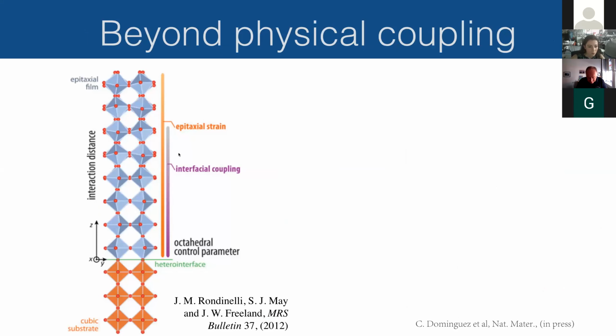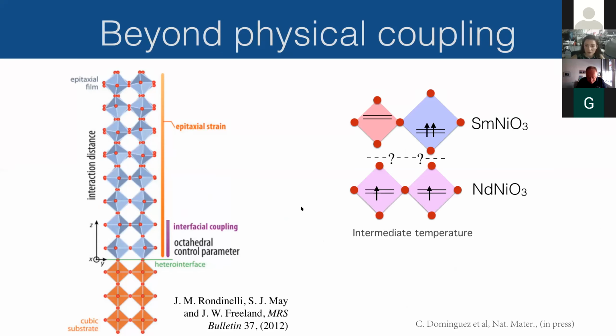So what we say, if I go back to this picture from this nice review, is that the interfacial coupling here is so small that it really can't explain what we see. Instead, it turns out that there is a cost of having an interface between the two materials at certain temperatures. So at intermediate temperature, samarium nickelate wants to be insulating already, but neodymium wants to be metallic. So you would have this kind of mismatch, and then it's not clear what the system would do.